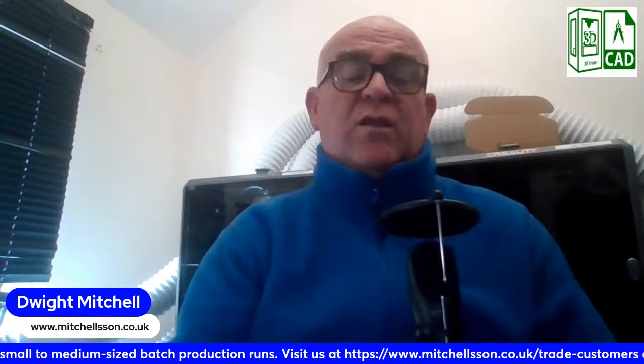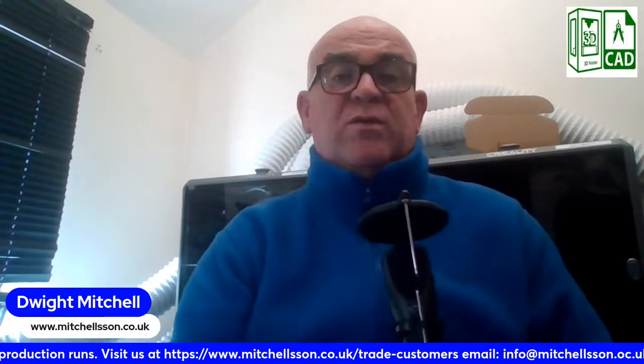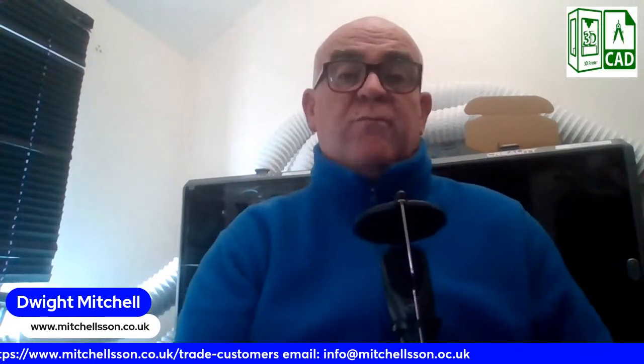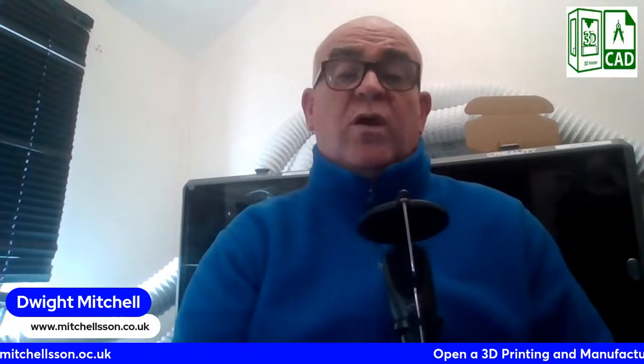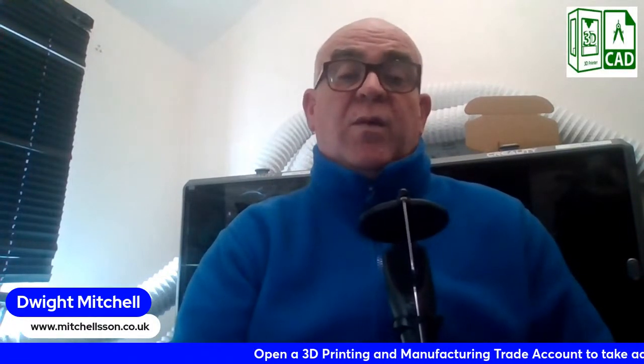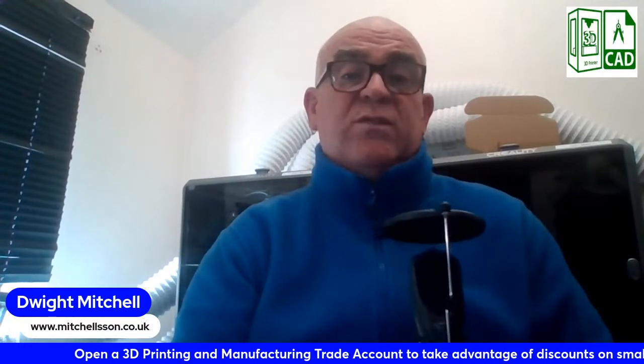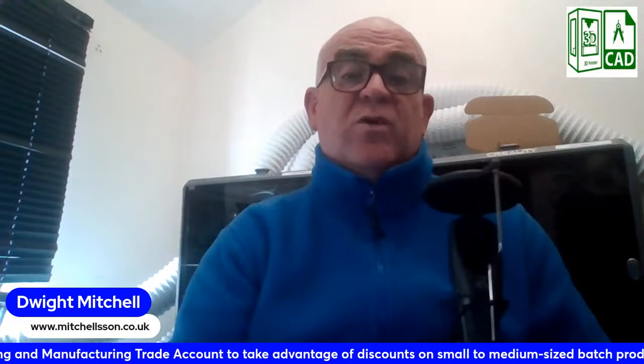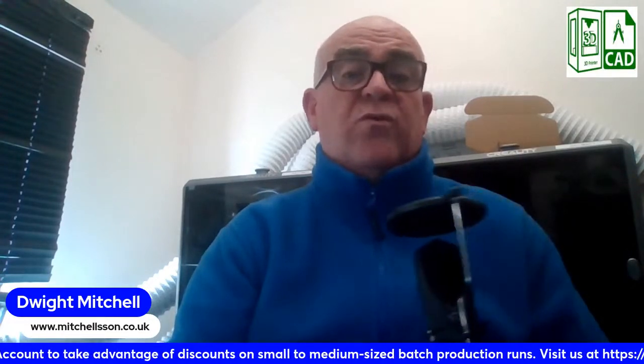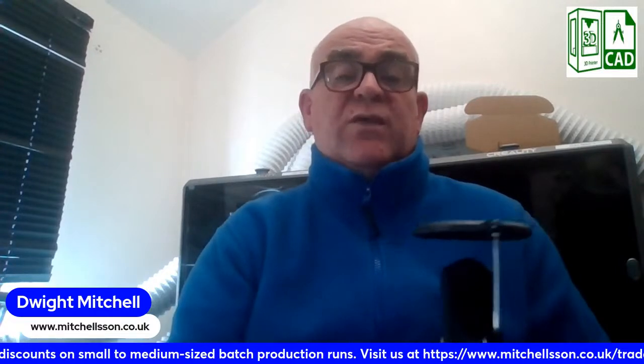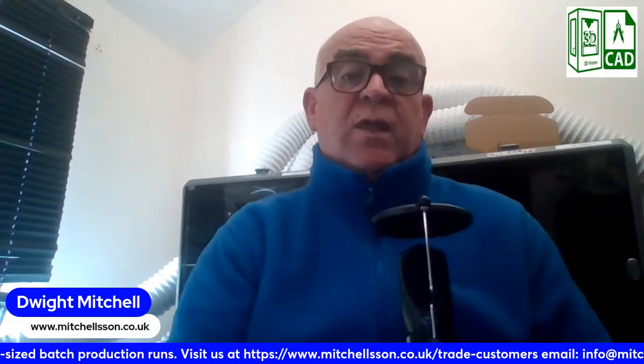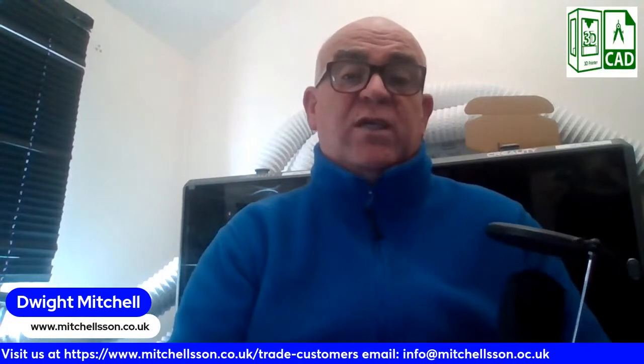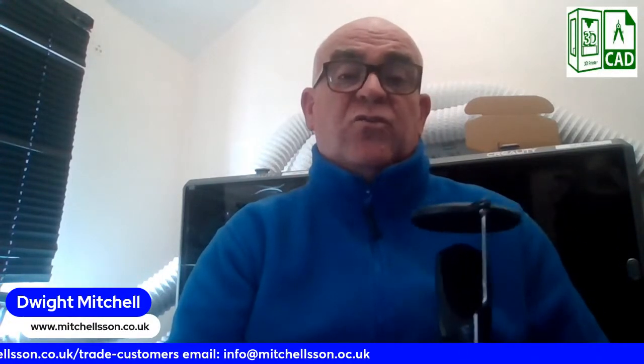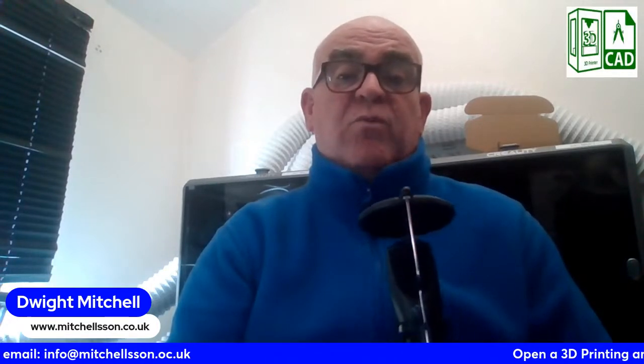So there's polycarbonate. It's something that I think has been around for a while within the 3D printing industry. It's something we provide and we offer, and it's quite a good choice for engineering applications. The tensile strength can be up to 70 MPa. The flexure strength is up to 100 MPa, and the Young's modulus is up to 2.4 GPa. You've got an impact strength of 70 kilojoules per meter squared. It's got a high heat resistance of 150 degrees C. It's also good for UV resistance, but with prolonged exposure, it can start getting a yellowing effect.